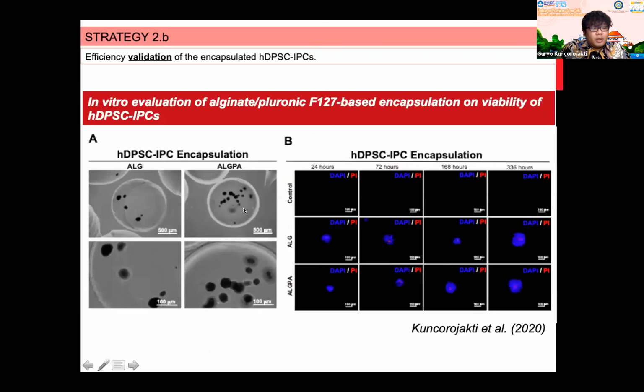In this study, we did microscopic observation of encapsulated IPC in both encapsulation platforms, alginate alone and also alginate pluronic acid. The findings show that the cell aggregates here were unequally dispersed. And for the analysis, we didn't see any aggregate damage during this experiment. Then we evaluated the viability of the encapsulated IPC under the capsules using a simple method. We just use live/dead staining and observe under the fluorescence microscope.